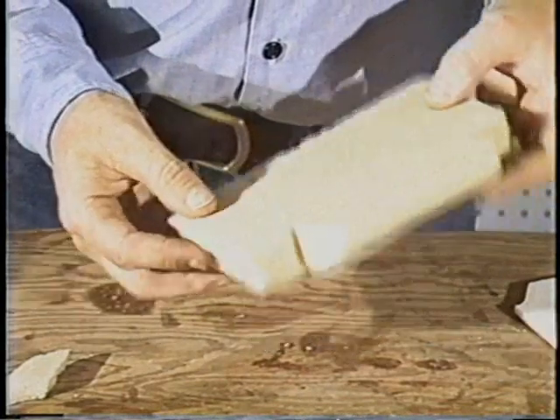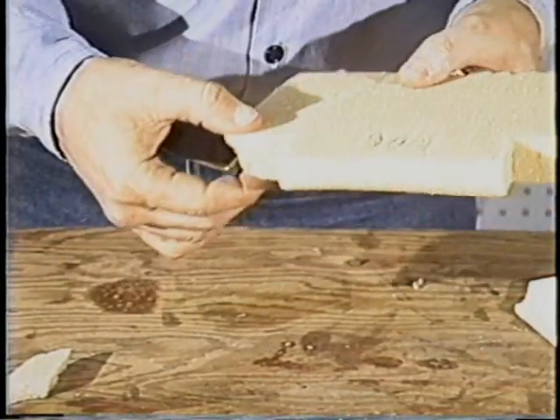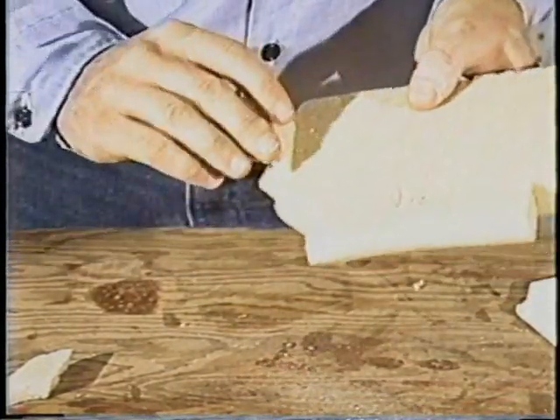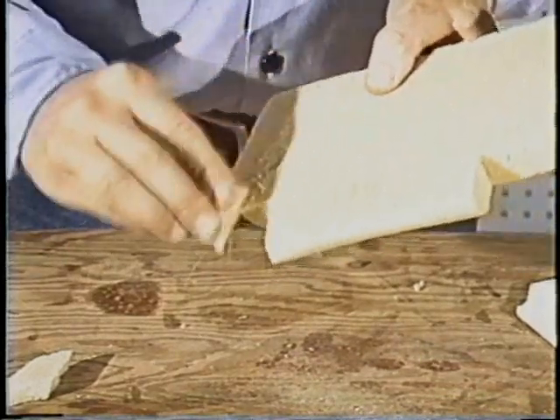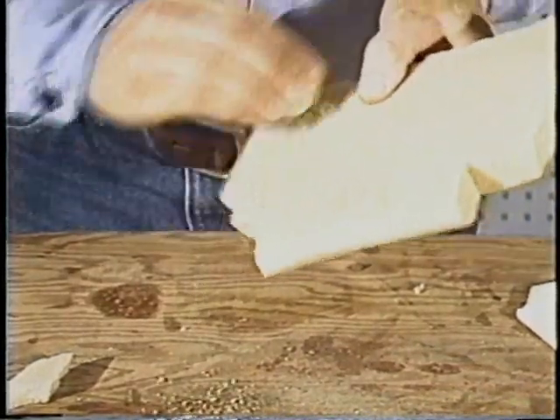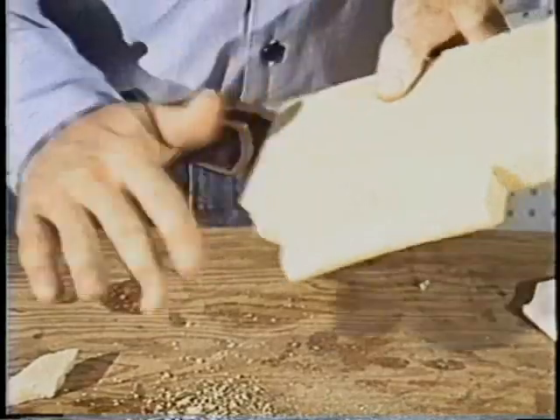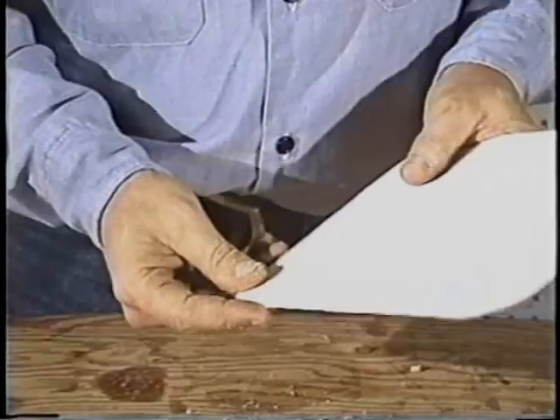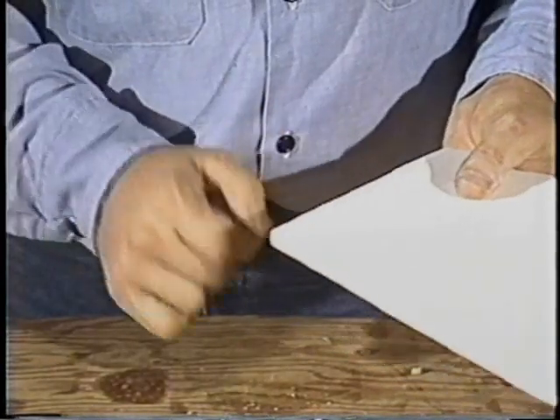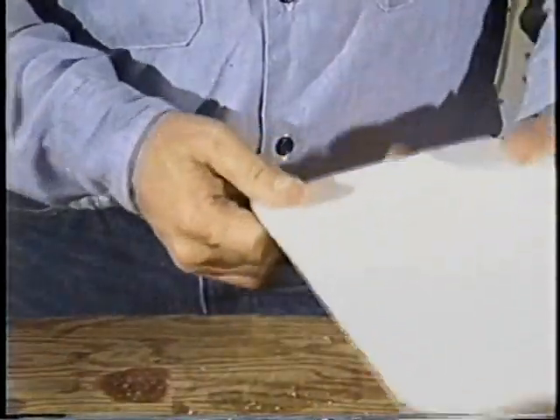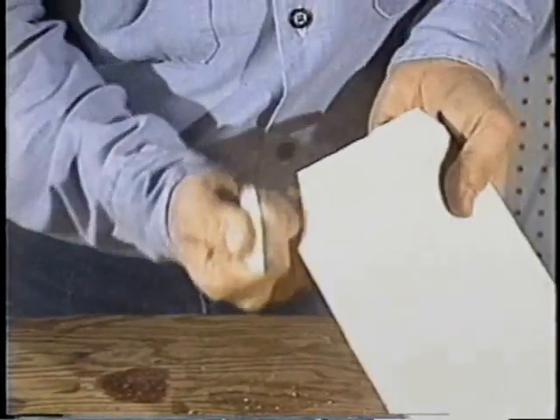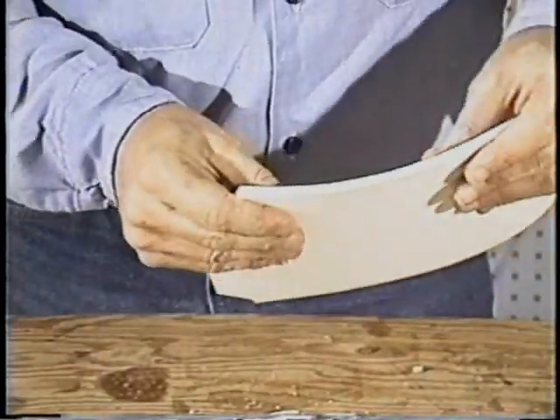Urethane, by contrast, has a very low inherent strength, but it is amazingly easy to shape. Most forming can be done by just a few strokes of a sanding block or even another piece of urethane foam. The strongest of all the foam cores is Clark foam, a thin core material with a high compression strength. Because of Clark foam's strength, it lends itself to be used for hardware attachments, bulkheads, and instrument panels.